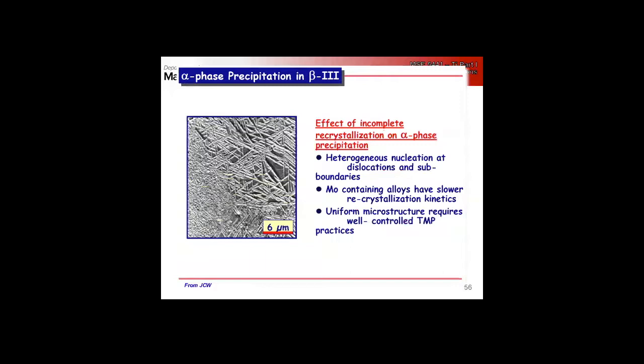I threw this slide in here because molybdenum is added to some of these alloys to slow recrystallization kinetics. Right, if we can slow recrystallization, we maintain a dislocated structure, so we have better alpha nucleation sites.